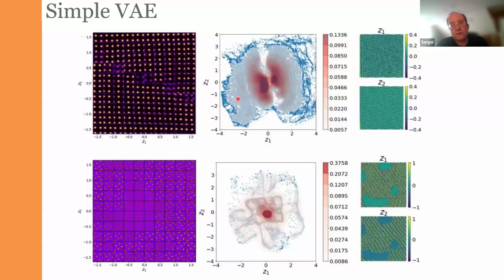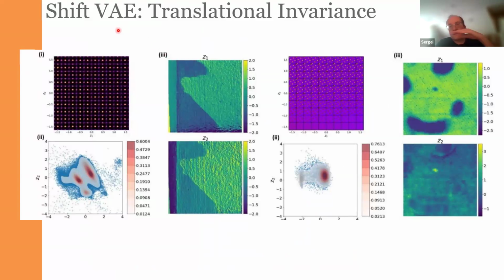So this is the example of how you use these VAEs with the adding invariances in order to unpeel the onion of the physical mechanism inside the system. So we use the simple VAE. It gave us the complex latent distributions and very unphysical latent images. So clearly we did not discover what the relevant physics is in this case. We took a slightly more complex VAE that separates the translation from other factors of variability. And lo and behold, our remaining factors of variability are physically relevant. So these are the ferroic variants and the difference between ferroelectric and substrate. Our latent distributions are very well behaved, and everything else makes perfect sense. So once we get something like this, we can say that our VAE analysis of the data has been successful.